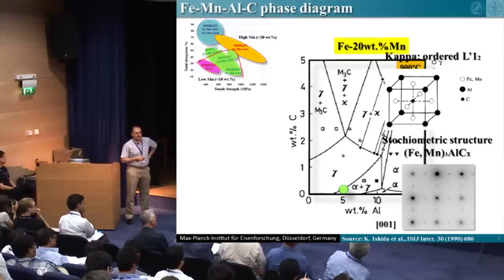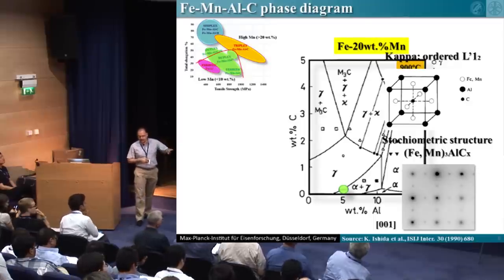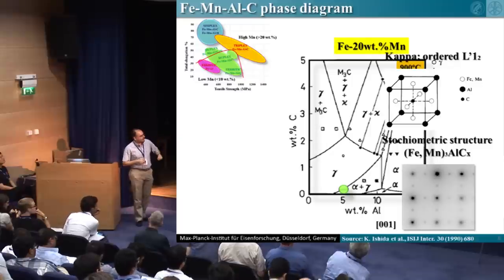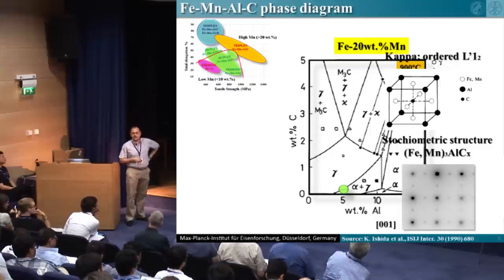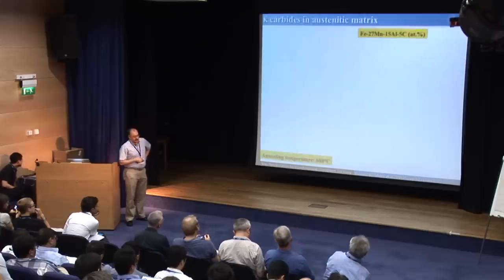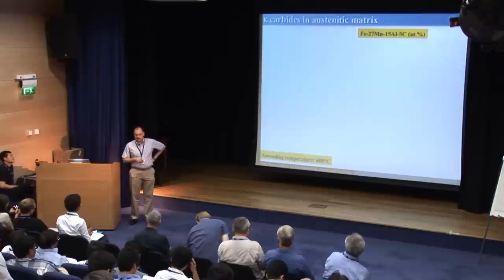If one goes to the TEM, no problem at all, because one can immediately perform tilting experiments, just placing a zone axis, and immediately realize that this is an FCC structure. Apart from that, no more information. Now I would like to show you the difference in the kappa phase, whether the matrix is austenite or ferrite. So in the austenitic matrix, here is an alloy that we are currently investigating in our lab,